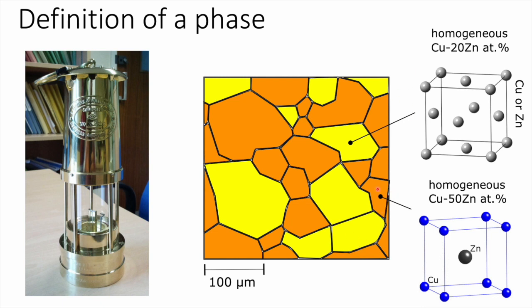The second orange crystal is much richer in zinc and is an ordered phase: the copper atoms are at the corners of the cube and the zinc atom at the middle, or vice versa. The composition of the orange phase is much richer in zinc than the yellow phase, and yet when these are in equilibrium with each other, there is no tendency for the zinc to homogenize between the two structures — essentially the same problem as the salt between ice and seawater.